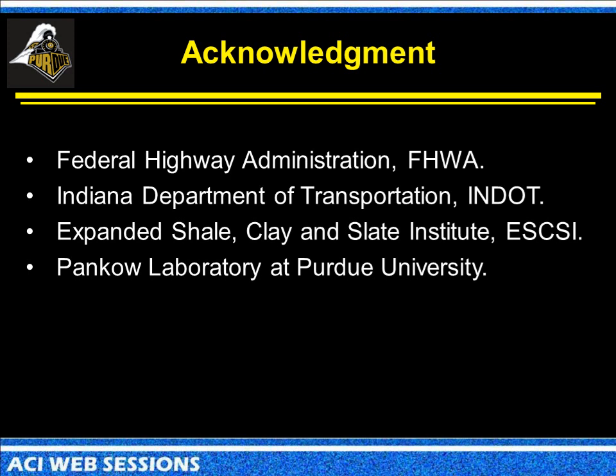I know Doug mentioned earlier limestones. You'll see the same concepts working with limestones, not necessarily because you're doing anything to the limestone, but you're allowing more water for the cement to hydrate, and you're taking advantage of that in the system. We can actually see, in some cases, we've actually replaced the fly ash altogether with a similarly sized inert particle, and we see similar benefits. Thank you.